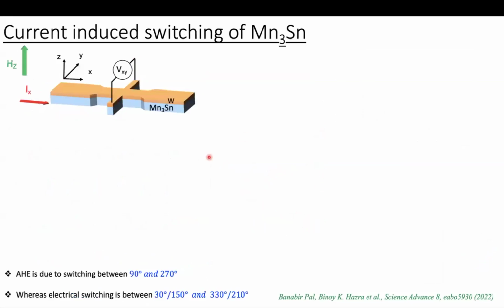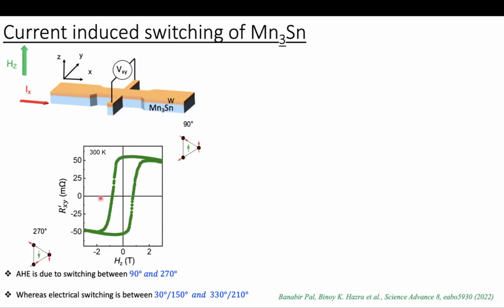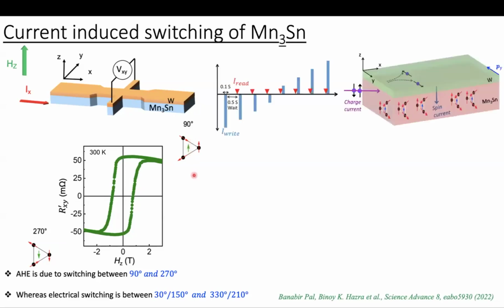Then the entire structure was fabricated into a Hall bar as shown here, and we apply a small DC current, 1 milliampere, along the X direction, and sweep the out-of-plane magnetic field, that is along the Z direction, and measure the transverse voltage, which is nothing but anomalous Hall resistivity. And what do we observe? We observe a large hysteresis. The coercivity is around 1 Tesla. And the magnitude of Hall resistance from, let's say, top to bottom is nearly 100 milliohm. Among these 6 domains, the 90 and 270 degree domains are involved in magnetic field induced switching, as the net moment, shown in green arrow, is along Z or minus Z direction.